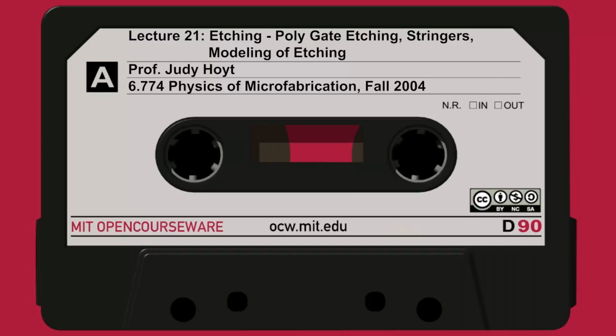And I apologize, this is not a very good SEM. I took this off the website again from that IBM article. And what it is on the very top there is photoresist that has been etched, that has been patterned, I should say. Then there is a layer of tungsten silicide that has been etched. And then there's a layer below it of polycrystalline silicon that's been etched down to, say, the oxide, that's down to the gate oxide. And when presented with something like this, you have to think about using 2 different types.